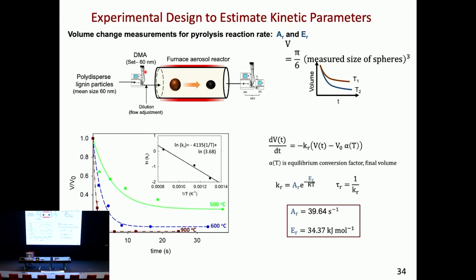I would want to change the size, which we do, and do this for a series of sizes to ensure that this is independent of particle size, which it turns out to be. If it turns out to be a function of particle size, there's a lot more head scratching to be done to ensure that we account for some of these things.